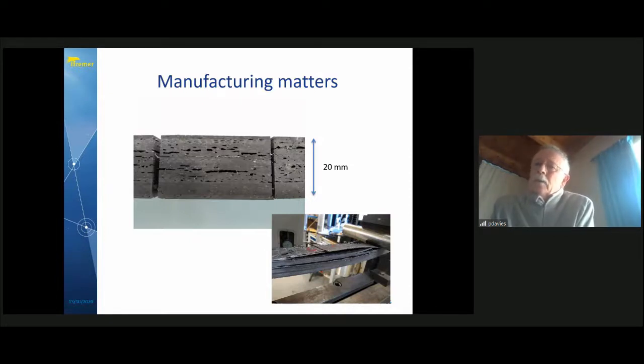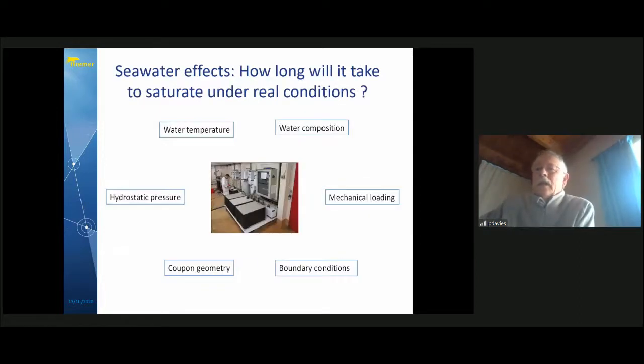And this is just one example of a 20 millimeter thick panel, which we did some work on, again, within the Sabella project to look at the influence of defects. And you can see a very high proportion of porosity. And as soon as you start mechanically loading this, even in static loading, you see a very big drop in performance. So those kind of parameters, you need to have quality control, you need to follow the manufacturer, and you need to be sure that the material that you have on your blade is actually the material you've been testing in your qualification procedures. Next, please.